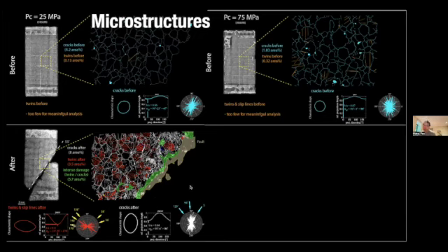These microcracks are preferentially oriented parallel to the loading direction. So that tells us that those are mode 1 cracks. And all these red features, which are either twins or slip lines, tend to be oriented oblique to the loading direction at about 45 degrees. So that tells us that those are probably defects that are activated based on the maximal resolved shear stress.